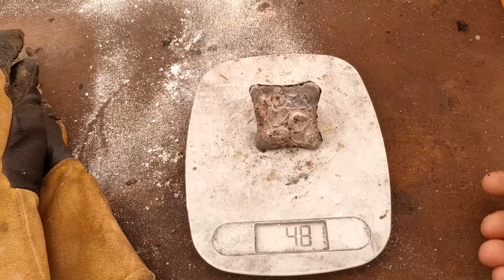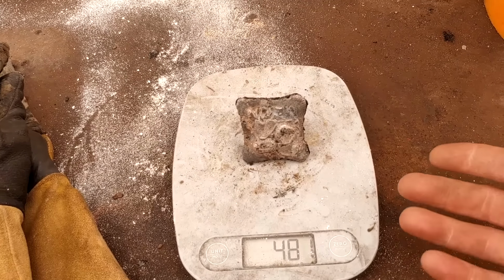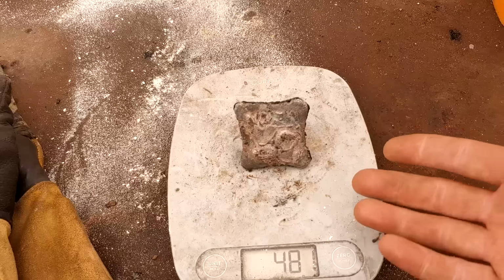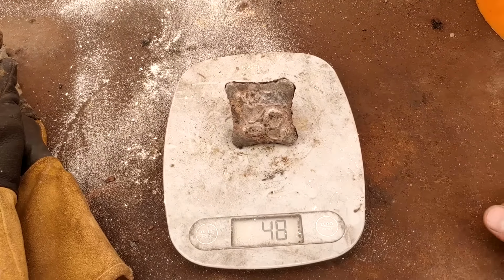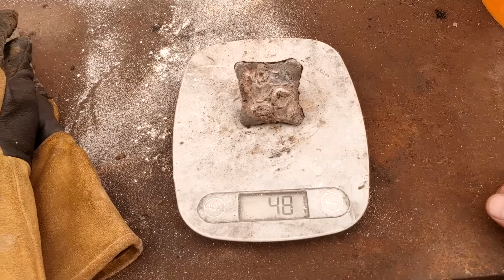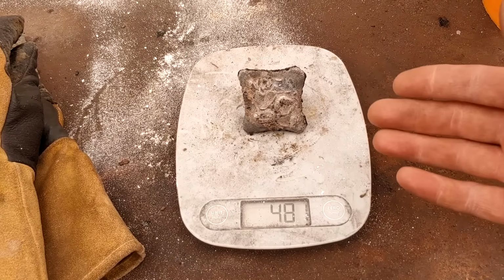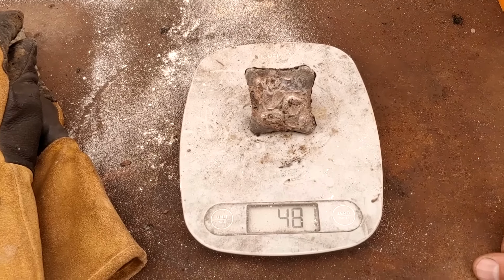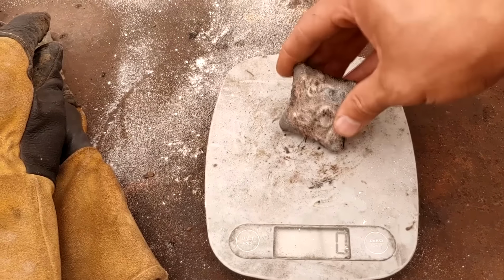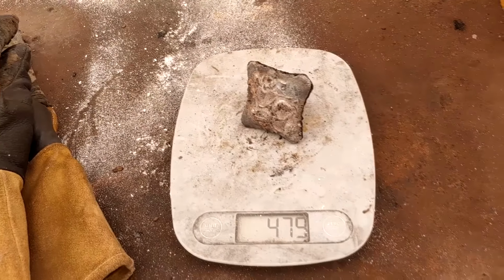And maybe if I left it in the furnace a little bit longer, or actually, now that I'm thinking about it, we may have lost a bunch of metal in the bottom of that furnace because the crucible leaked. So anyway, it's not really a conclusive test on how much you can recover from your slag, but we recovered a significant amount, even though we probably lost an appreciable amount in our furnace.